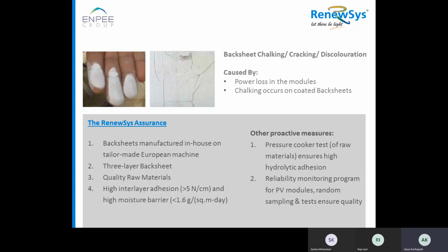You know that we also manufacture backsheet in-house in our Bangalore factory in India, and these machineries are from European technology. We make a 3-layer backsheet, and for all the raw materials of the backsheet we go for a 3-step methodology where we qualify internally, extended reliability, and third-party testing. Our backsheet has high interlayer adhesion, greater than 5 Newton per centimeter, and high moisture barrier, less than 1.6 gram per square meter per day. We also do a pressure cooker test for backsheets. We also do reliability monitoring for PV modules randomly and test to ensure quality.